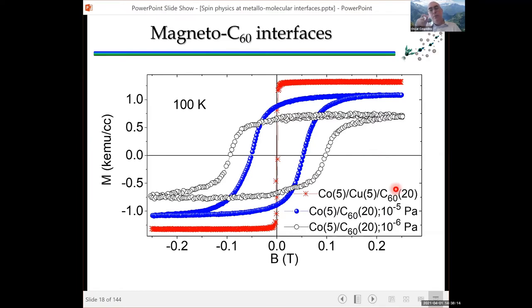So if you do this at a better vacuum, then the coercivity is even bigger and the magnetization is even further reduced. So the coupling between the molecule and the metal, as you would expect, is very affected by any oxygen, or water in particular, that can be in your chamber. So you need to be in the 10 to the minus 10 millibar partial pressure of water if you want to see these effects.